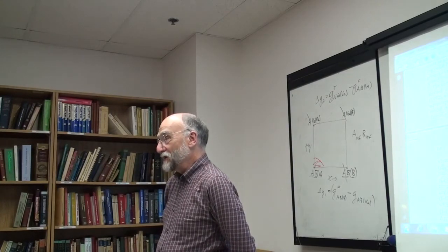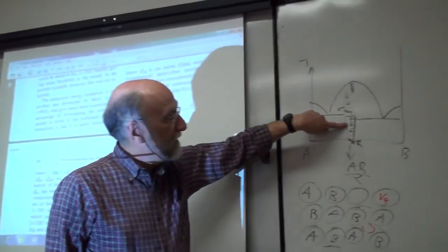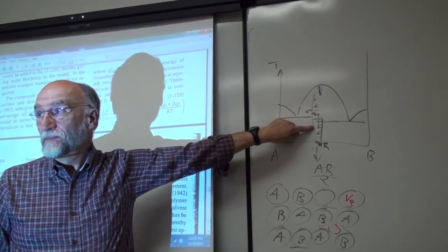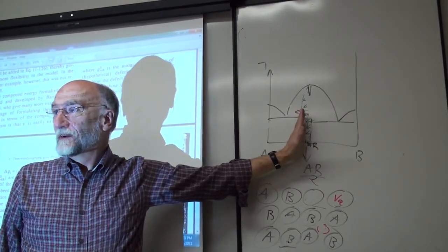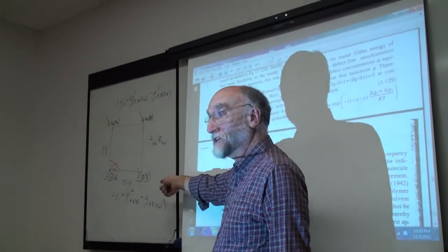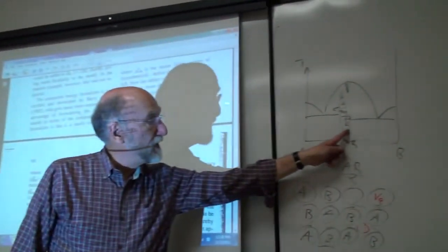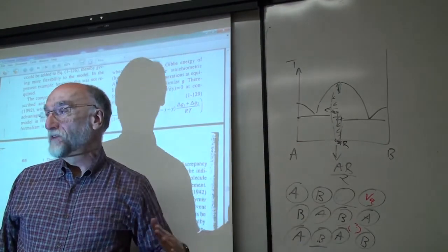Well, some thermodynamic data is going to give you more information than others, if you're trying to model the system. If you measure the solubility limit here, in other words, measure the phase diagram, you know how far that's gone over. That permits you to get a value of G naught. That's the easiest way to do it. Then, if you measured the activity coefficient of A as you moved across, all you'd find would be a straight line.